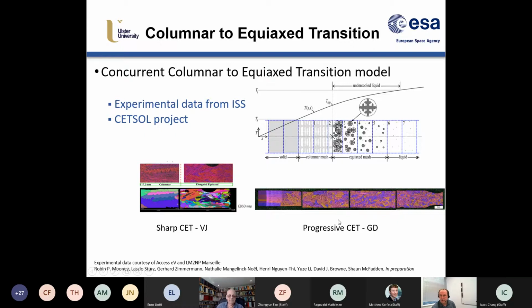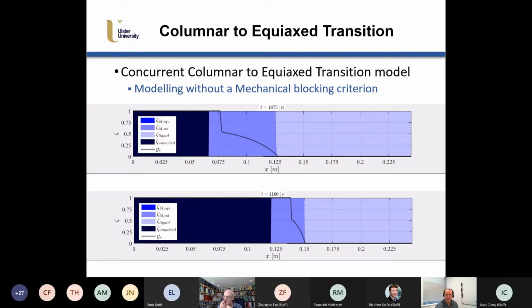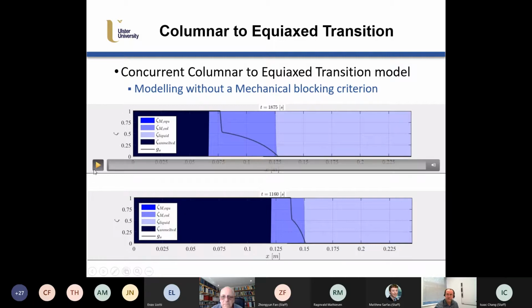And then when you do gradient decrease, you see that it is best described as being majority columnar to begin with, and then majority equiaxed at the end. And even at the end, you'll see very clear evidence of elongated columnar grains within the structure. They become less prominent at the end, but this is what we call a progressive CET. So it's not a sharp CET. So how to capture this? Well, we used the Nucleation Progenitor Function approach for equiaxed, and we used front tracking for the columnar.